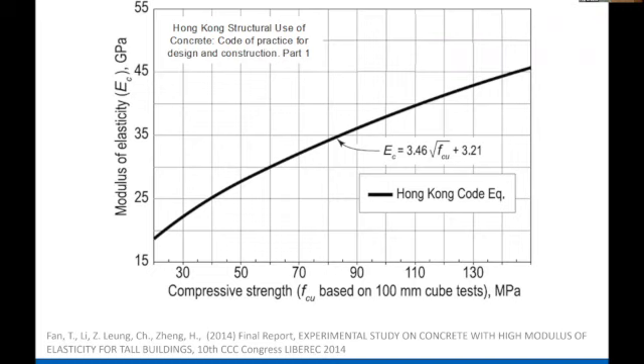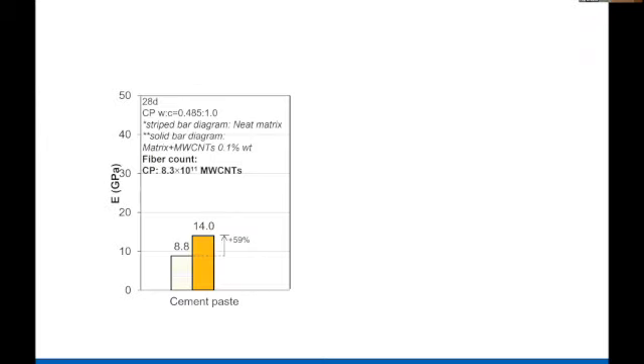After that workshop, I went to our group in our lab and noted we had not really paid much attention to modulus with the addition of nanofiber, carbon nanotube. Here I have shown the modulus of cement paste with 0.1% multiwall carbon nanotube. And you can see we increased the modulus by about 60%. But this is carbon nanotube added at the nanoscale in the cement.